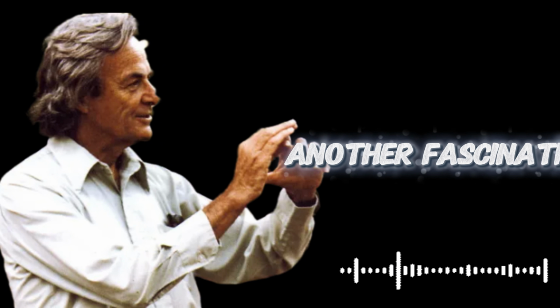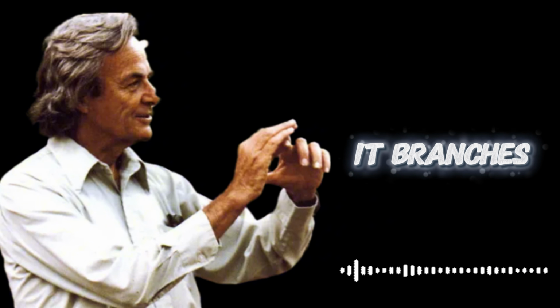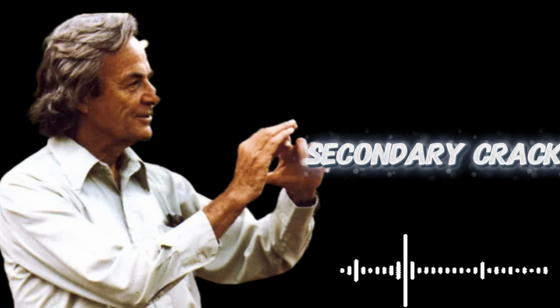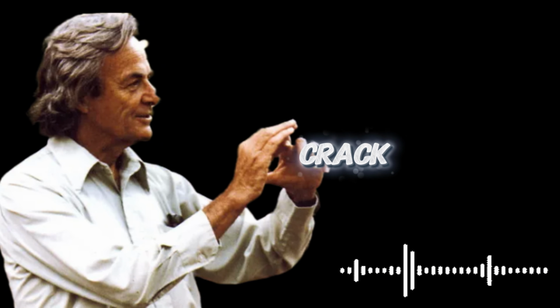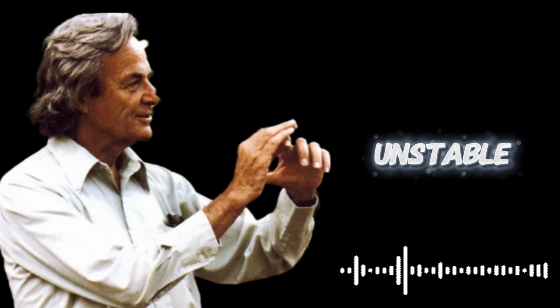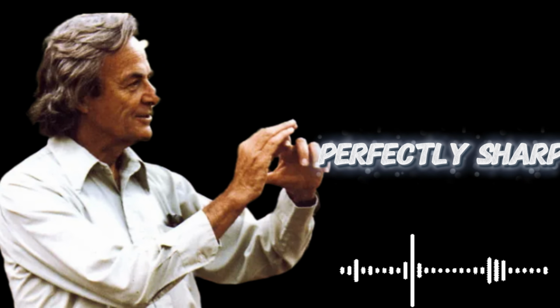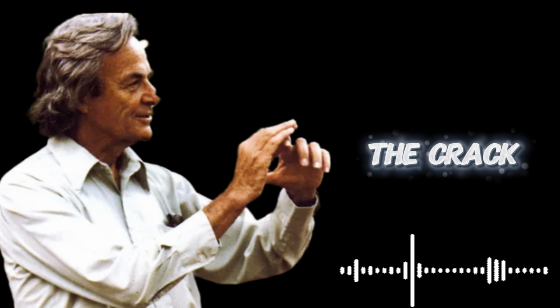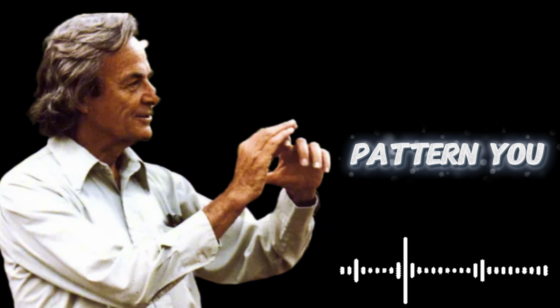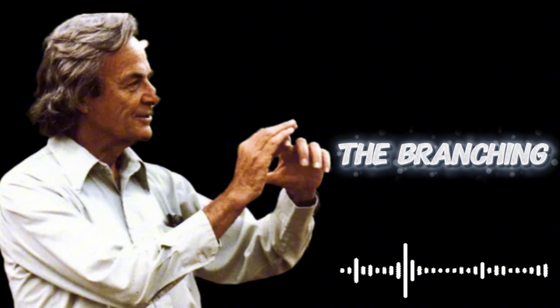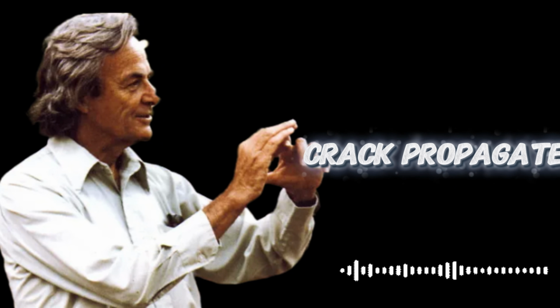And here's another fascinating thing. As the crack moves through the glass, it doesn't just go in a straight line. It branches. It creates secondary cracks. Why? Because as the crack accelerates, it becomes unstable. The crack tip isn't perfectly sharp. It's rough at the atomic scale. Small perturbations get amplified. The crack forks, creating that characteristic pattern you see in shattered glass. The branching pattern, the fracture surface roughness, all of this records the history of how the crack propagated. It's like a fossil record of the breaking process, frozen in the fractured surface.